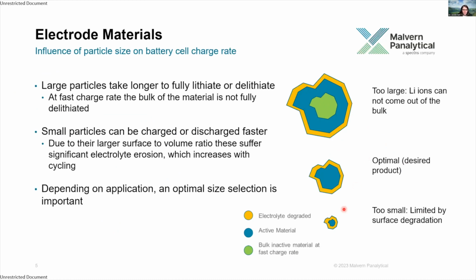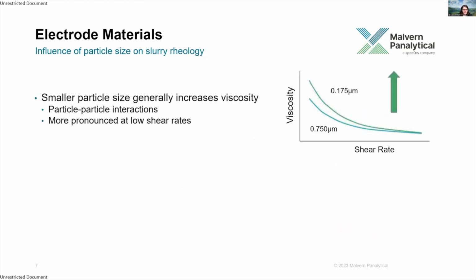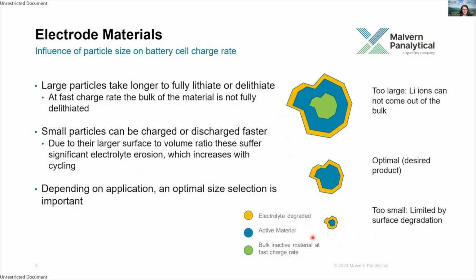As the particles get smaller, they can charge and discharge faster due to their larger surface area to volume ratio, but they'll also suffer from a lot more electrolyte erosion at the surface of the particles, with this degradation increasing with cycling. So the desired particle size of the cathode material is therefore a balance somewhere in between. Generally, large particles will hold lots of lithium ions and they will have good specific energies, while the large surface area to volume ratio of the small particles enables lithium ions to be transferred between the electrolytes easily, so they can generate a lot of current, leading to high specific powers.